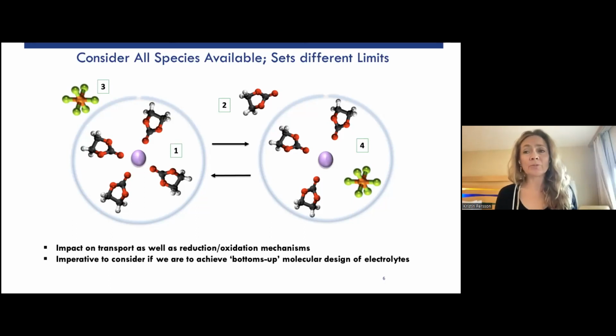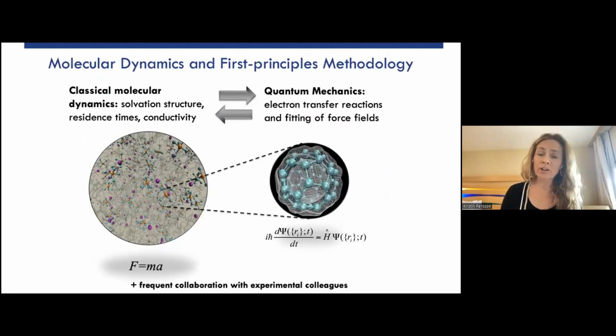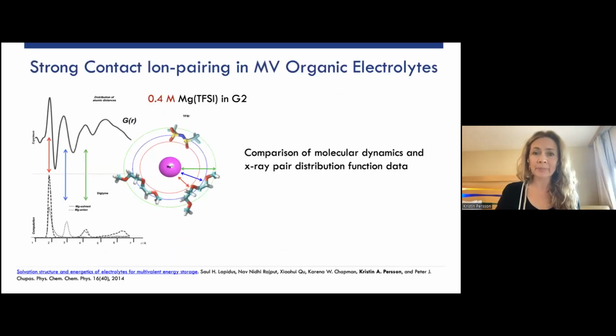And this is really important if we are to consider a bottoms-up approach to designing electrolytes, because if one of these minority species is unstable, you have an equilibrium that feeds the formation of more of those in the bulk of the electrolyte and may actually become the limiting case. So in this first part of the talk, I'm using mostly classical molecular dynamics to get an idea of the solvation structure in the bulk electrolyte. And I'm using quantum mechanics simulations to get an idea of reactivity, so reduction and oxidation reactions, as well as helping me to fit the force fields for the classical molecular dynamics.